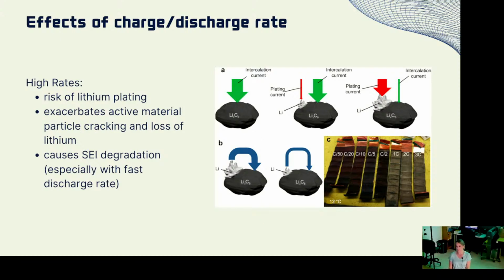And then the risk of lithium plating. I love this diagram and this picture here. This is with a graphite anode, and what this is showing is different charging rates. You see C/50 on the far left and then 3C on the far right. But you notice the color of the electrode is different across that. The darker ones show no lithium plating, but when you see that gray color on the right, that's an electrode that has had lithium plating happen to it. So when you take apart a battery, you can visibly see this plating sometimes, and that's why the lower rates are often safer for a cell.